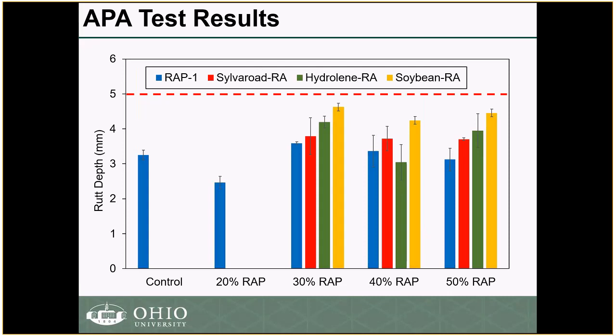We also did the asphalt pavement analyzer to evaluate rutting because we have seen that there might be some softening. And all mixtures have met the criteria, which is 5 millimeters for mixtures with medium traffic. The only thing here that I would like to note is that using a softer binder increased the rutting, but it is not that significant; in all mixtures the rutting was not really high. The rejuvenator or the recycling agent, to a certain degree, some of them have resulted in a higher rutting, specifically the soybean that you see here. Again, that is an indication of the softening effect of that recycling agent. But in general, all of those mixtures in terms of rutting met the criteria of less than 5 millimeters.